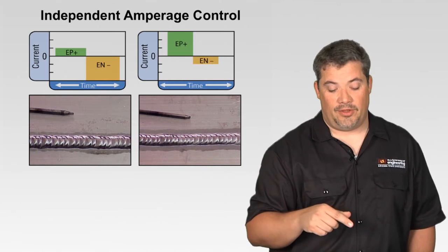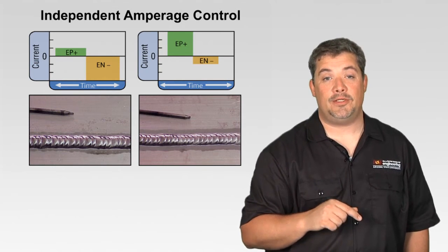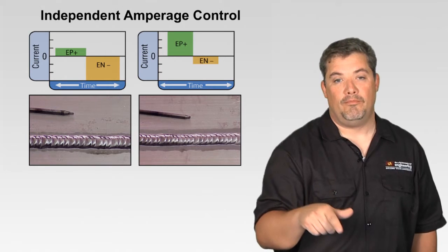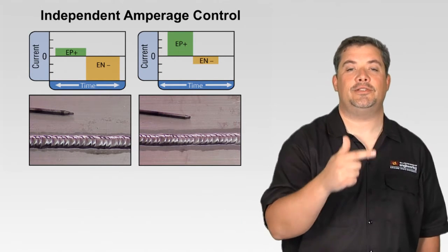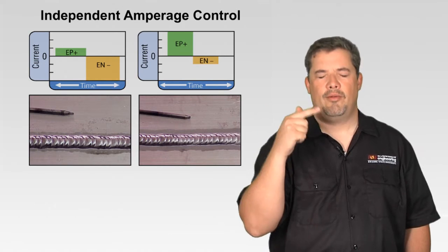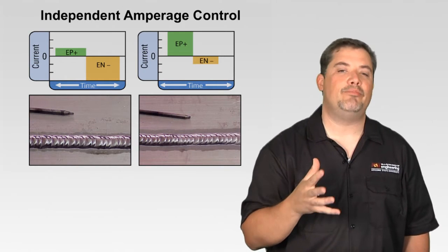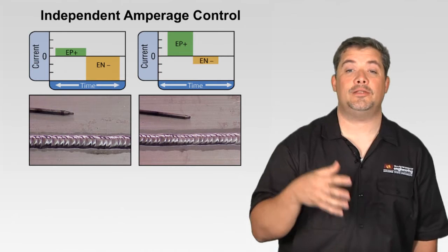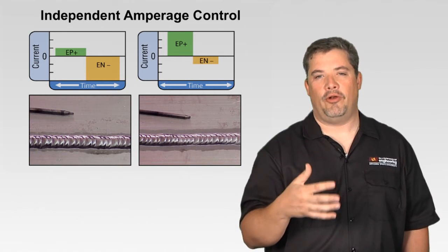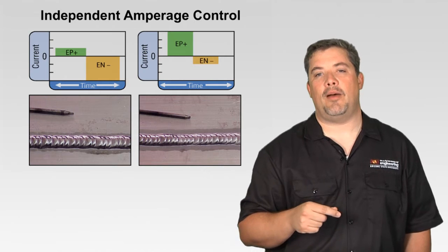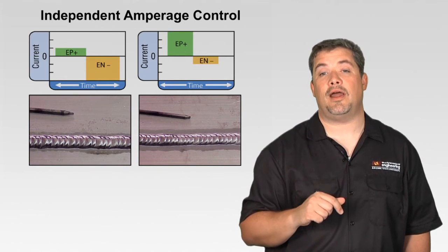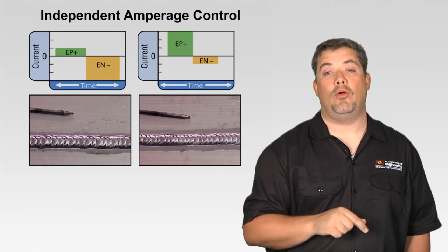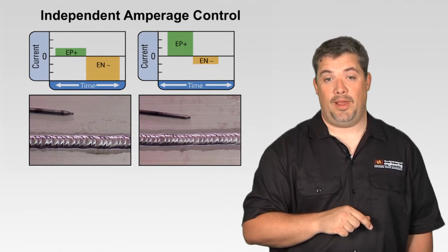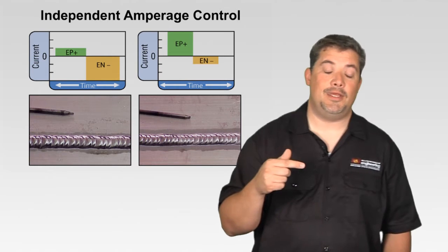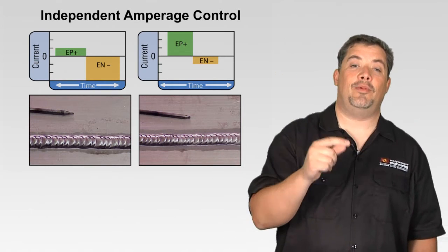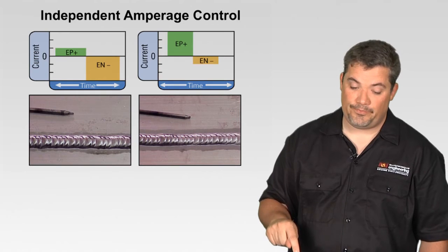So on the image on the left, you can see we used a lot of electrode negative amperage, equal time, sharp tungsten, minimal etching, because that positive half etches the oxide layer, the negative half puts the heat on the part. It's all about finding this balance that works for the part, how clean the part is, the aluminum alloy you're running, but it makes you a more efficient aluminum welder. On the right, you can see a lot more electrode positive amperage. You can see the tungsten got a little more melted, and you can see more etching happening. And both these welds were made with zero high frequency, so debunking the idea that high frequency creates that etching. It's all about the electrode positive that creates that etching.